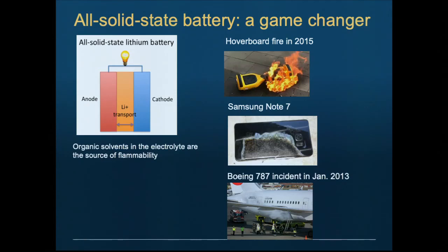The primary driver for solid state is safety. The reason is what makes a lithium battery flammable is not the lithium, it's the organic electrolyte. We use an organic electrolyte, a carbonate solvent, which has a very low flash point. The typical incident in the battery is one of two. Cells get punctured in an accident, electrolyte leaks out, you're in a high voltage environment, you have sparks and things blow up on you. Or the other one is you have an internal short. In an internal short, the battery releases its energy very rapidly. The cathode is highly oxidized. It oxidizes the electrolyte, because the electrolyte is an organic solvent, and you have an explosion or fire internally.